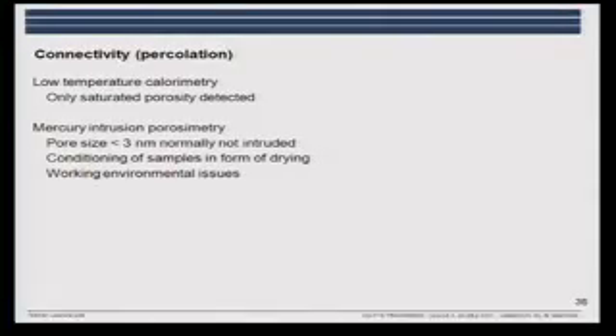The methods we can use to determine the connectivity are low temperature calorimetry, where we have to consider that it's only the saturated porosity which is detected. It's the freezing of the water; if there's no water in the pores, there is nothing to detect. And then mercury intrusion porosimetry, with a lower pore size limit, typically 3 nanometer, but that depends on the pressure you're using. We have to consider the conditioning of the samples in the form of drying, and then there are working environmental issues. I know that several have taken down their instruments because of these issues with mercury.